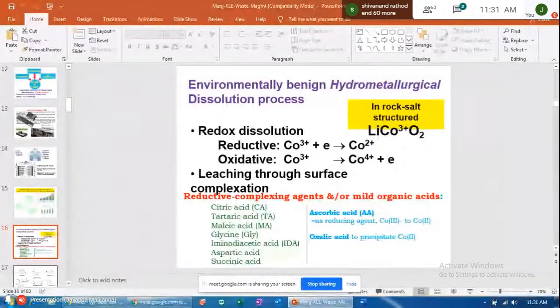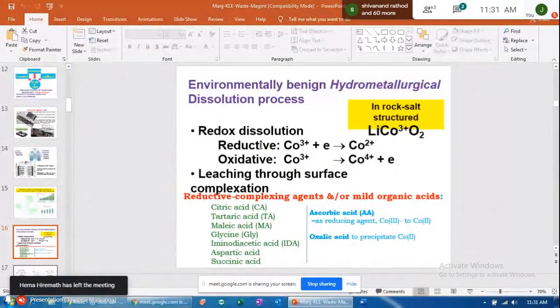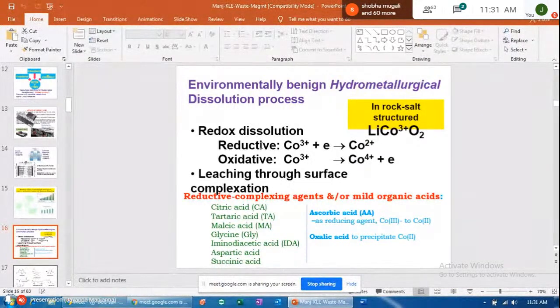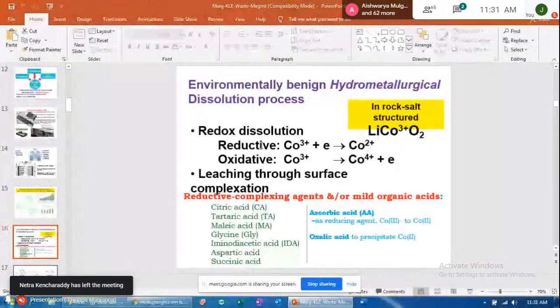Here in lithium cobalt oxide, cobalt is in the +3 state, as I said. Now you can subject that material to redox dissolution, either reductive dissolution or oxidative dissolution. Reductive dissolution reduces cobalt 3 to cobalt 2. Cobalt 2 is bigger in ion size, so it gets ejected from the lattice and gets stabilized by the chelating agent present in the dissolution medium. Similarly, oxidative dissolution is also possible, where you oxidize cobalt 3 to cobalt 4 plus using certain oxidizing agents. So as a redox dissolution method, it seems very interesting.